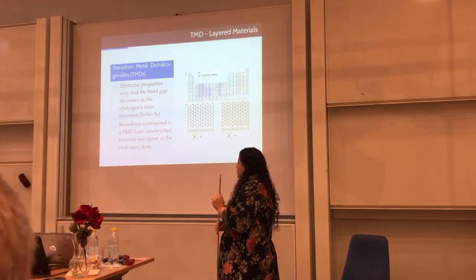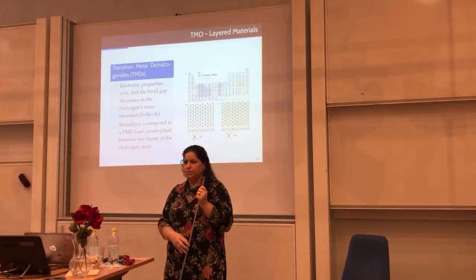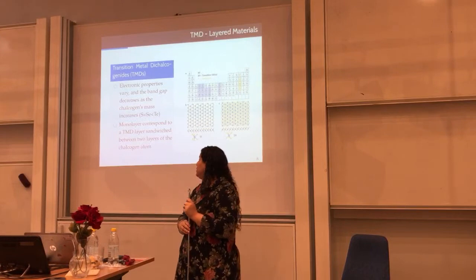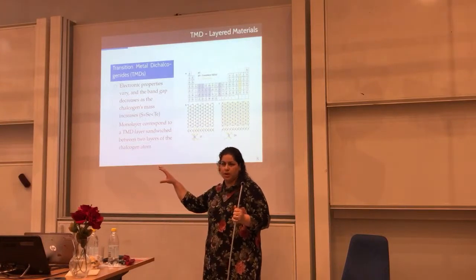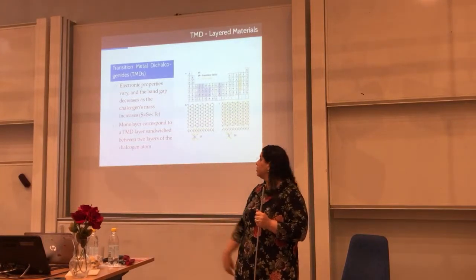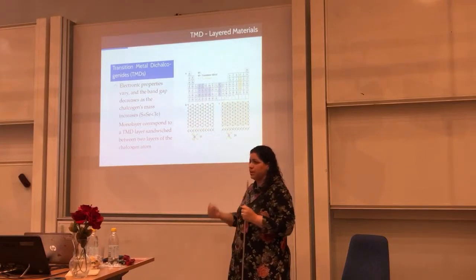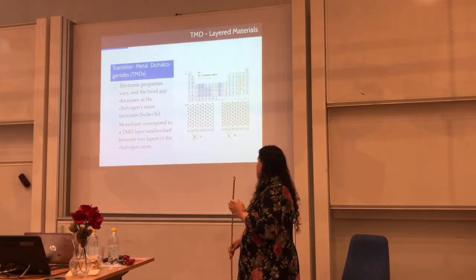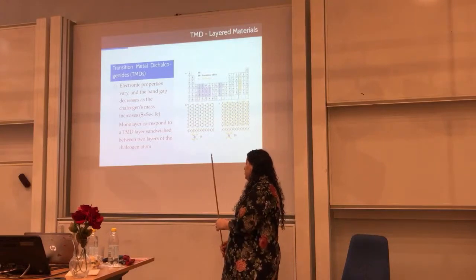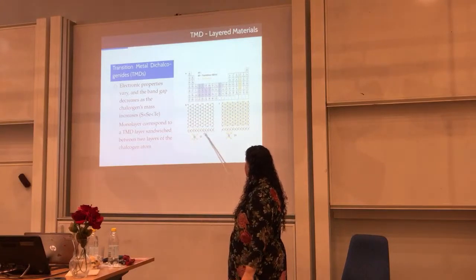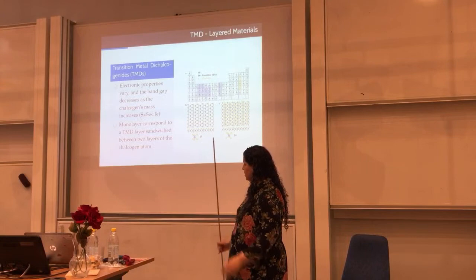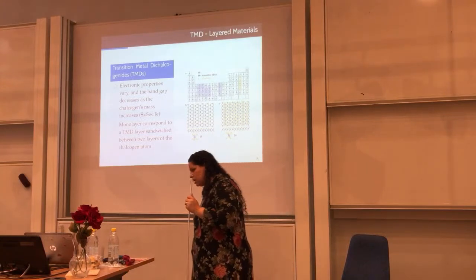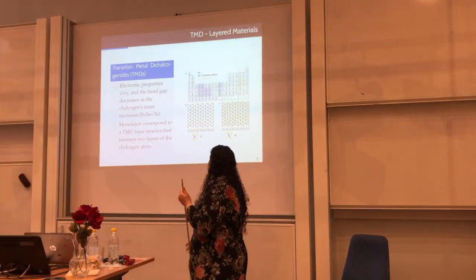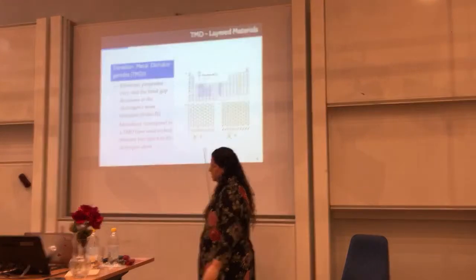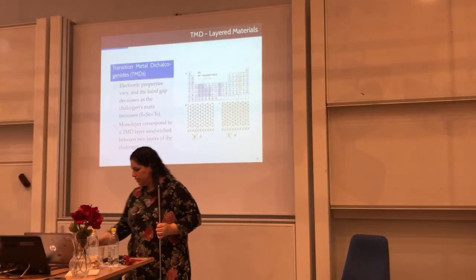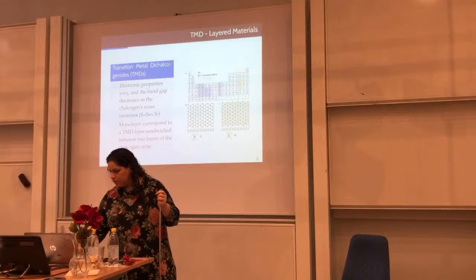The difference between a monolayer of molybdenum sulfide and graphene is that in graphene you have a monolayer of carbon atoms. It's just one layer of atoms. And in molybdenum sulfide, you actually have three layers. You have the metal, the molybdenum, in the middle, and the chalcogen atoms sandwiching the molybdenum, which makes the three atomic layers.